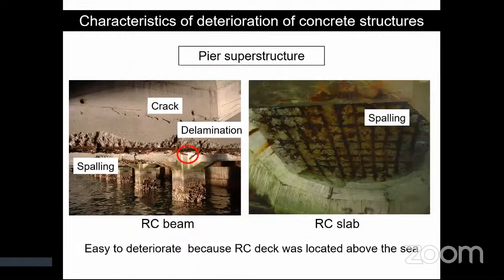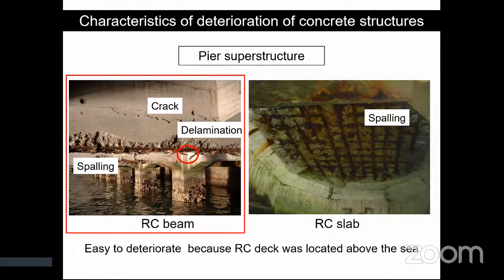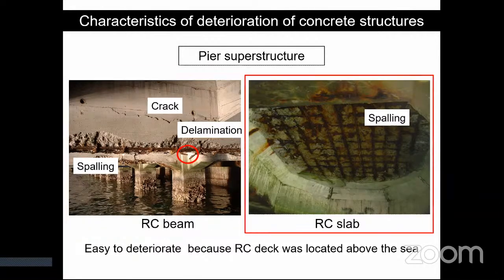These pictures are typical examples of deterioration of members at pier superstructure due to corrosion of steel in concrete. Left picture shows deterioration of RC beam. There are cracks, delamination, and spalling occurred at concrete member due to corrosion. Also, right picture shows deterioration of RC slab. The spalling of concrete occurred same as RC beam.